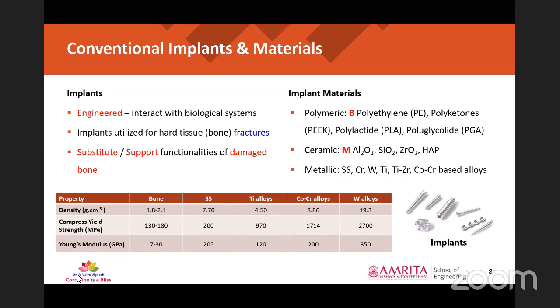And coming towards metallic implant materials, researchers and medical people have been using stainless steel based, chromium, tungsten, titanium based alloys for implant applications. However, when we check the property of these conventional materials with the bone, which is given over the table over here, we could observe that the density, compressive yield strength, and Young's modulus of these conventionally used metallic implant materials are very much higher than that of the bone itself.